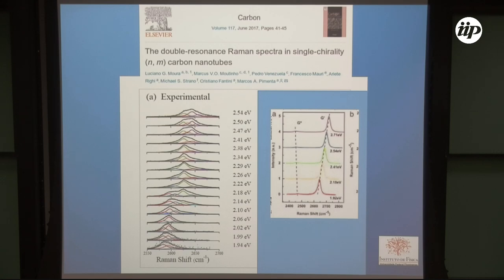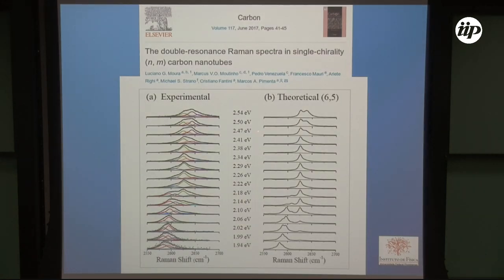And this is the theoretical calculation by Marcus Moutinho. Okay? He did that for a (6,5) carbon nanotube. So in the calculation, we see some similarity in the sense that also the peaks are not symmetric, and on average, they are dispersive. What's the reason for the difference between this peak in graphene and this peak in carbon nanotubes? The reason is very simple. You can think about a nanotube as a sheet of graphene that's rolled up. When you do that, you now have quantization in the radial direction.